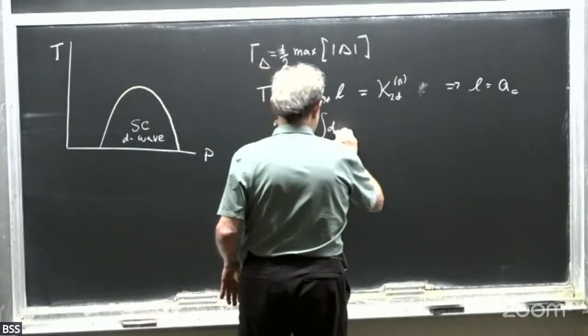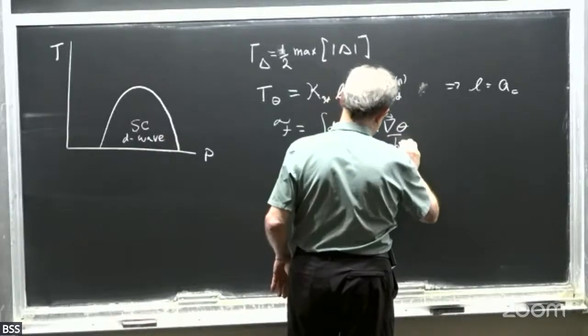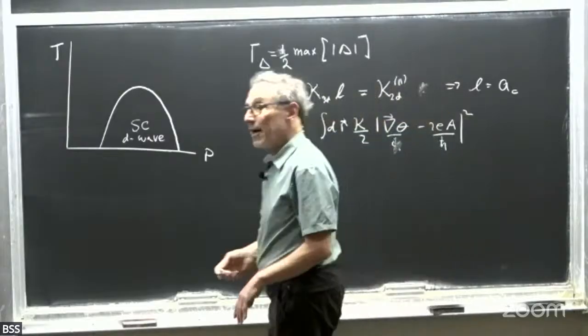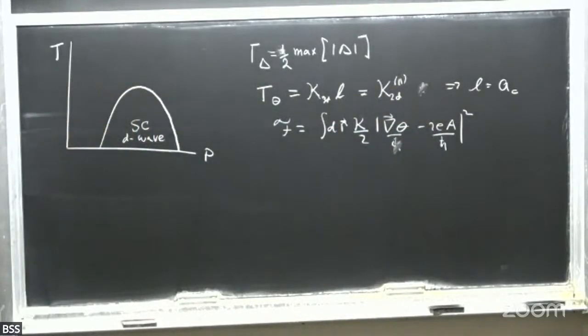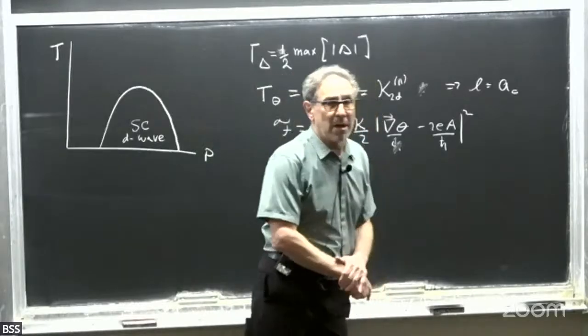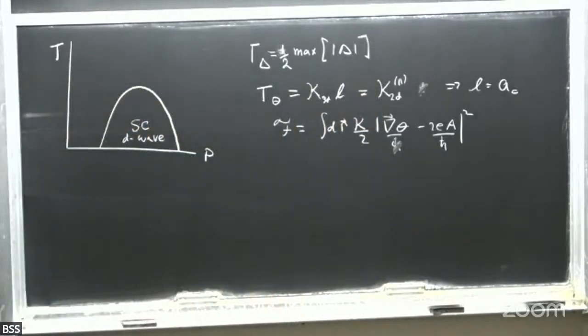And what is kappa? Kappa is the coefficient in the low energy description of the collective modes of a superconductor. Kappa is the superfluid stiffness. And in 2D in particular, you can see it's of energy. And so kappa characterizes the temperature scale at which phase fluctuations, collective fluctuations of the order parameter, would be expected to destroy long-range phase coherence.